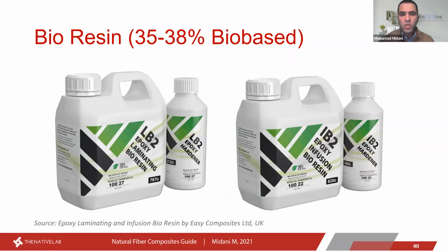So let's look at some of the commercial bio-based resins that are available in the market. These are bio-based epoxies that are supplied commercially by Easy Composites, okay? The LB2 is a laminating bioresin, an epoxy bioresin. The IB2 is an infusion resin, so it's more suitable for vacuum-assisted resin transfer molding and resin infusion applications, okay? Both of them have bio-based content of up to 38%. This percentage of bio-based resin can provide epoxy resin with equivalent performance to the fully synthetic epoxy resin. And the price is almost 30% more expensive than the regular epoxy.